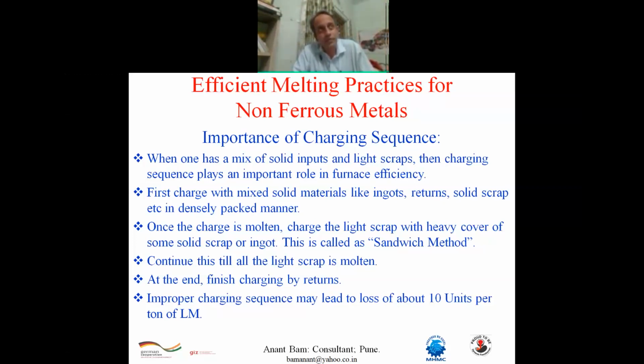Because unless there is some heavy material put on the top of turning boring, it will not enter or it will not get dropped into the molten pool. A small amount of turning boring which is touching the liquid metal or the heel metal at the bottom of the crucible will get melted very soon. But the turning boring which is above that will remain loosely packed. Now, if it is oily, then it will get heated, it will burn or char off, and that carbonaceous material will create further resistance in it. And all this vicious circle will lead to a gap between the two charged materials.